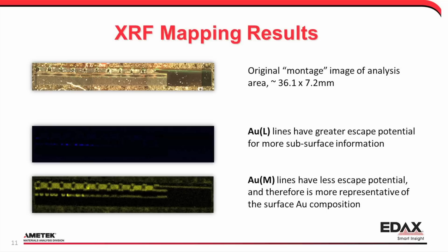That's the area that we mapped, and that was kind of a stitched field map using the video cameras on the Orbis. And so some of the elements that you would expect to see on a sample like this are gold, copper, tin, silicon, and various other elements like that. And some of the interesting things about the results, for instance with gold, is that we can map for gold L and gold M. We could add both series of lines for the spectral maps.